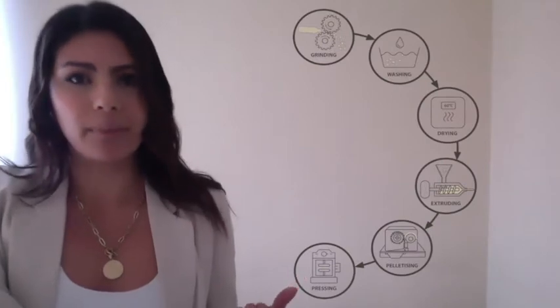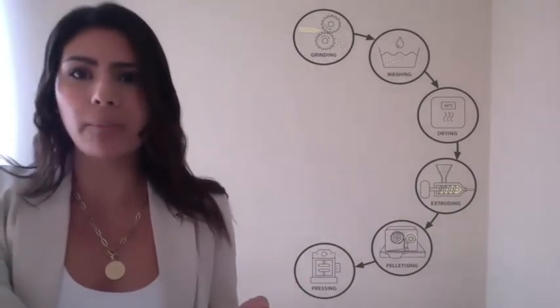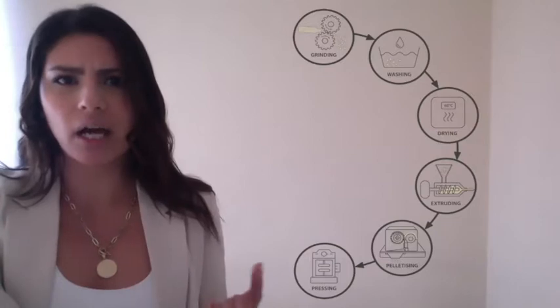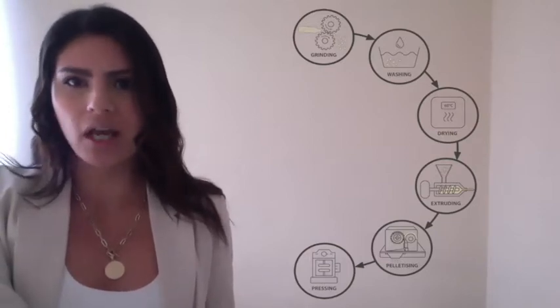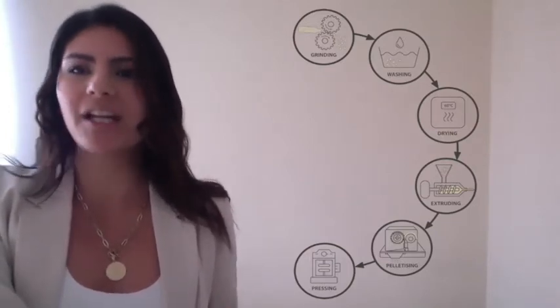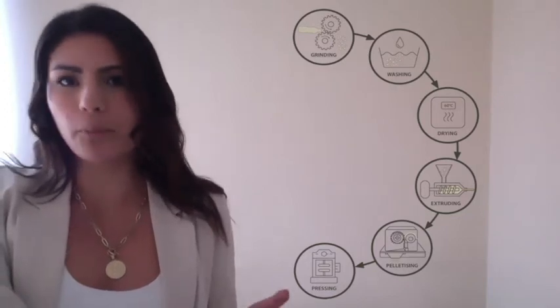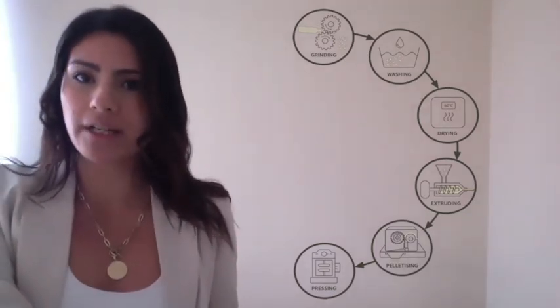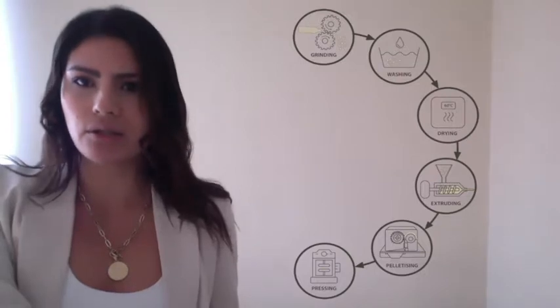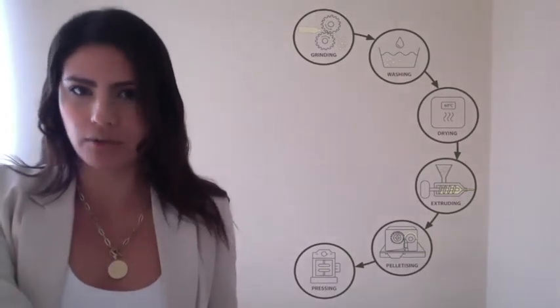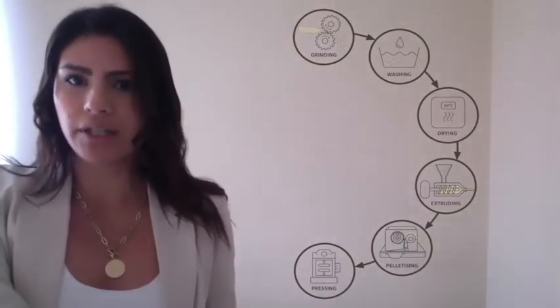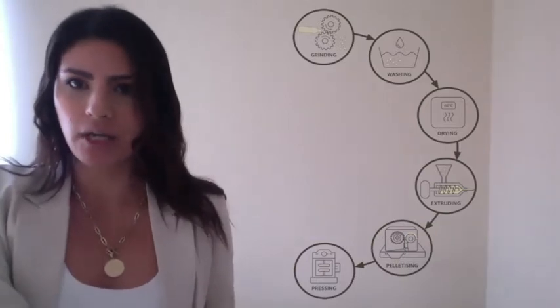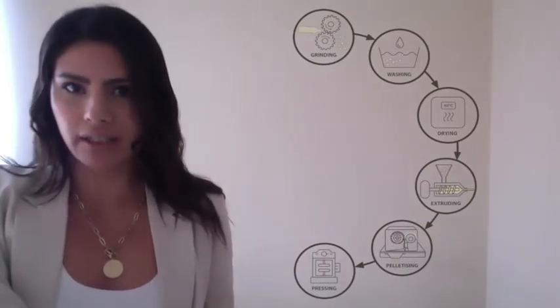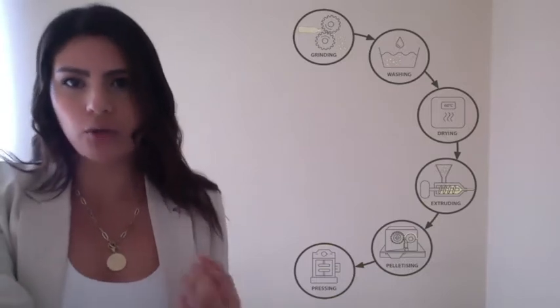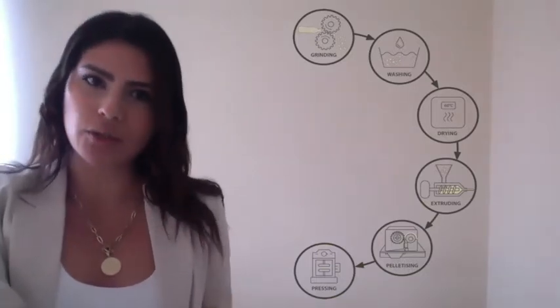As can be seen, PET waste is prepared by means of a mechanical process of grinding and washing and is readied to be mixed with the catalyst nanoparticles in an extruder, where temperature, pressure, and rotation speed variables are iteratively adjusted to achieve an optimal mixture. The newly extruded material, known as master batch, is then pelletized. Finally, the pellets are pressed according to different configurations of temperature, contacting time, and cooling time.